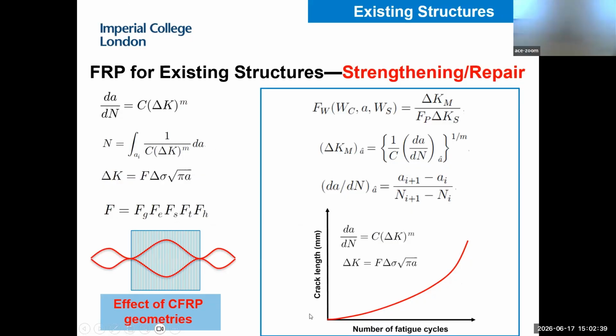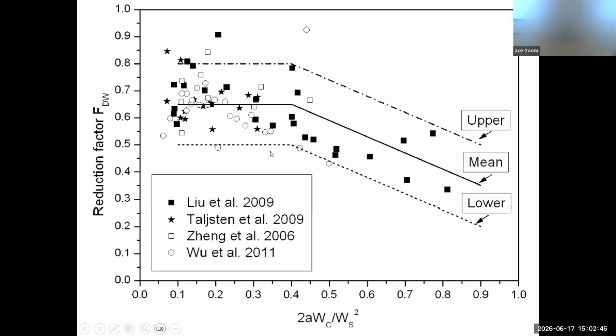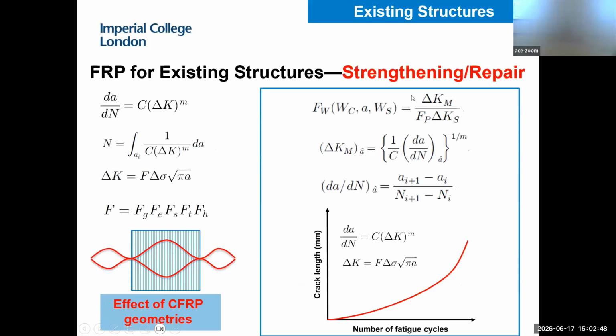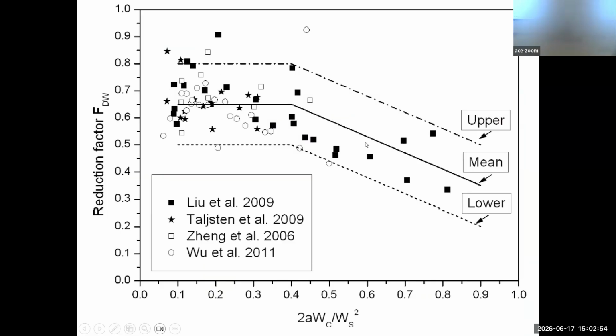Because we have a lot of experimental curves, we can calculate the experimental stress intensity factor, and from this we can calculate the modification factor. So we have a lot of data points on this figure. The vertical axis is the modification factor considering FRP geometry, and the horizontal axis is a non-dimensional parameter we introduced, because we believe the modification factor is a function of crack width, width of the CFRP, and width of the steel plate.